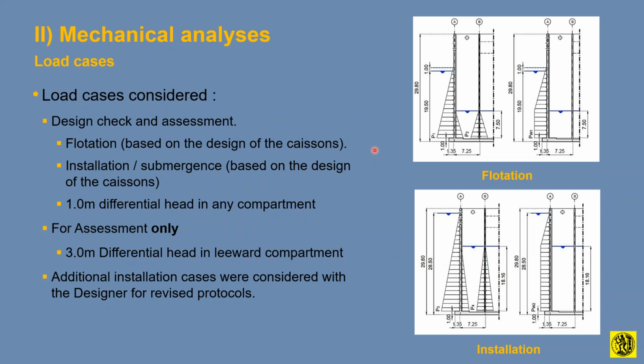So let's see the results. Now, the standard load cases for the design, to verify the design as well, are the flotation. For this specific caisson it was this condition here, whereby the external sea level is at 19.5 meters, plus or minus 1, and the interior ballast water is at 7.5. So this is a flotation condition whereby the caisson is floating and then it's gradually filled in to let go to the installation. Now, the installation phase is the most critical, because